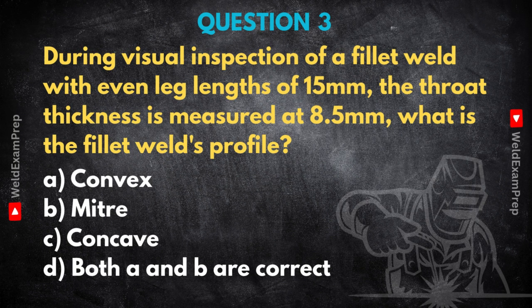So in this case, with 15 millimeter leg lengths, the theoretical throat for a perfect miter weld would be 0.707 times 15, which comes out to about 10.6 millimeters. 10.6 millimeters, but the measured throat was only 8.5 millimeters. Exactly. Our measured throat, 8.5 millimeters, is less than the theoretical miter throat of 10.6 millimeter. When the actual throat is less than the ideal theoretical throat, it means the weld face is sort of sunken in or dished, and that profile is called concave. Concave, like a cave, sunken in. Precisely. So the correct answer is C, concave.